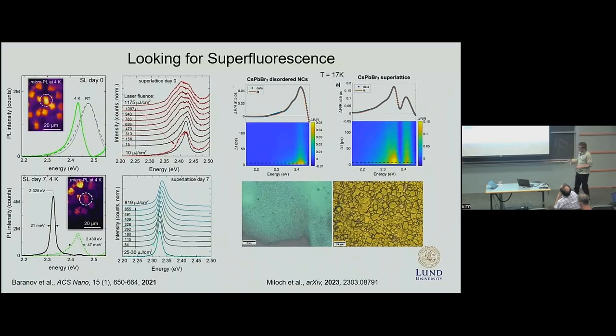Later we collaborated with another group, this time in Brescia, in the north of Italy. It is colder and drier, okay? We changed nanocrystals, used particles with different surface passivation, compared disordered film with a superlattice film, and in samples aged like a good wine for 90 days, we saw appearance of a new resonance in the transient reflectance data at low temperature, something similar to what was reported in 2018 from the Zurich group.